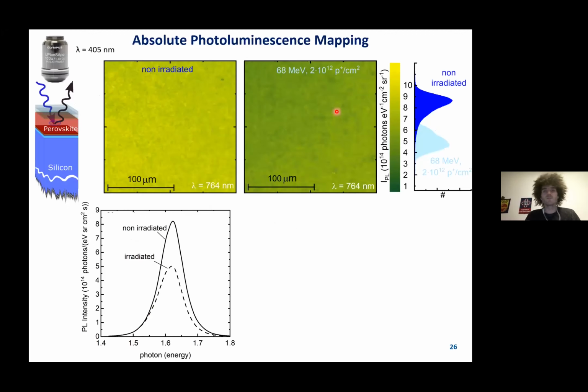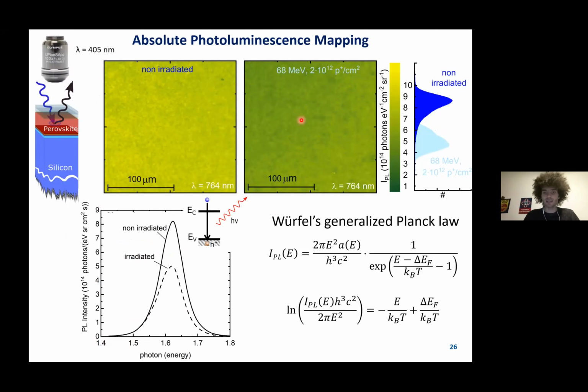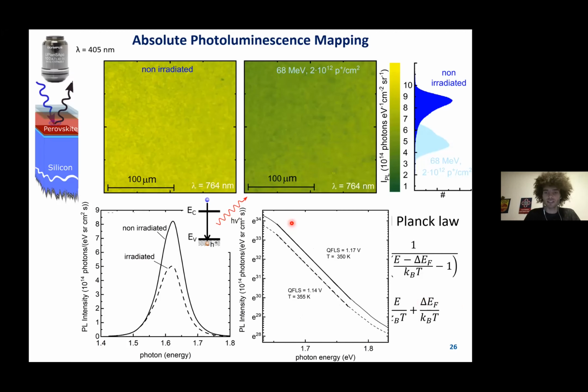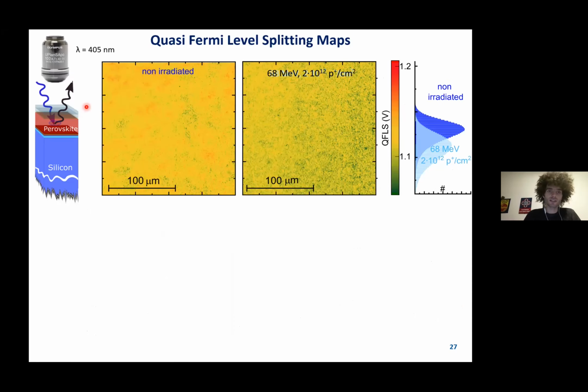So in order to find out, we then started to do absolute photoluminescence imaging, and we did that using a hyperspectral PL microscope in Cambridge. So we excite with a blue light laser, only exciting the perovskite, and record that PL. So the PL is, according to Würfel's generalized Planck law, a function of the quasi-Fermi level potential. So we have an equation relating the PL intensity to the quasi-Fermi level. And here I'm doing this with a linear fit at the high energy slope to extract the quasi-Fermi level splitting. And by doing that, we can create a quasi-Fermi level image.